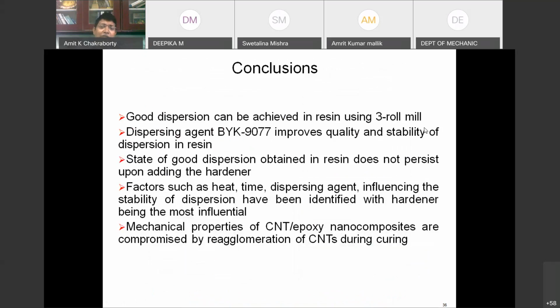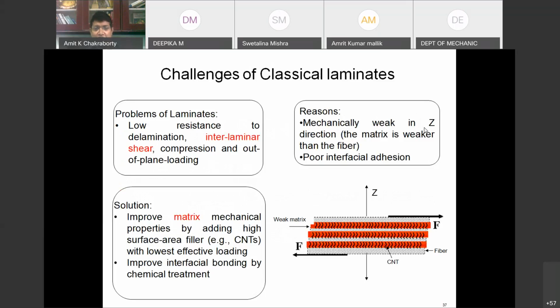So in conclusion, we found that dispersion and the interaction are the most important parameters before somebody can expect an improvement of the mechanical properties. Just mixing a good filler is not enough. How you mix, and whether the mixing is stable over the entire curing process, is very important to determine the mechanical properties of the composite. We have also used the same concept in making a laminate.